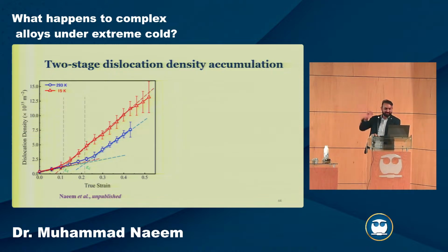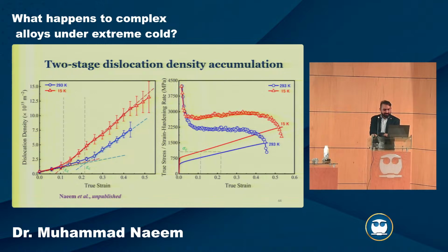So it had a two-step kind of dislocation accumulation. One is slower, and the second one is faster. But the faster one starts earlier for low temperature. And because dislocation density is higher at low temperature, and also it starts earlier, you have a higher strain hardening rate for this one. So this work is still unpublished, but we think it's very interesting that this one has only one mechanism, because the claim since the first paper was published is that when you have multiple deformation mechanisms, you can have an increase in ductility and strain hardening. But in this case, it is only dislocation slip, but still you see an increase in ductility at low temperature.